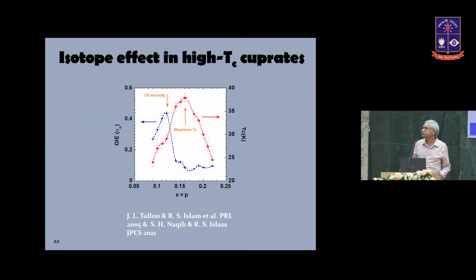This is the oxygen isotope effect. In the underdoped region where the superconducting TC is low, you have a very high isotope effect. But very strangely, where the superconducting transition temperature is maximum, the isotope effect is very low. And this low value of the isotope exponent persists in the overdoped region. So what actually are we looking at?